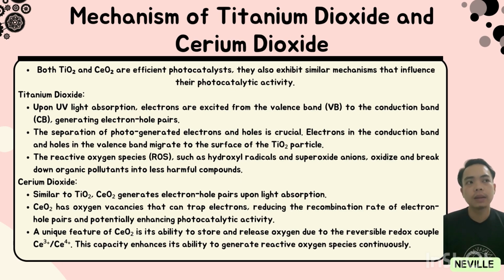They also exhibit similar mechanisms that influence their photocatalytic activity. Titanium dioxide and cerium dioxide generate electron hole pairs upon light absorption. Cerium dioxide has oxygen vacancies that can trap electrons, reducing the recombination rate of electron hole pairs and potentially enhancing photocatalytic activity. The reactive oxygen species in titanium dioxide and cerium dioxide will oxidize and break down organic pollutants into less harmful compounds. Cerium dioxide has a unique feature in which it has the ability to store and release oxygen due to the reversible redox couple. This capacity enhances its ability to generate reactive oxygen species continuously.